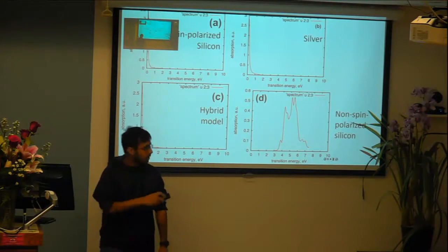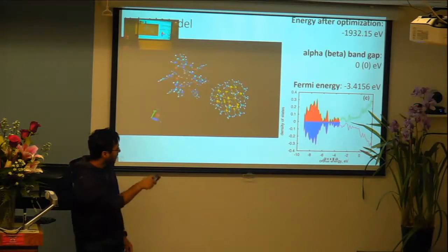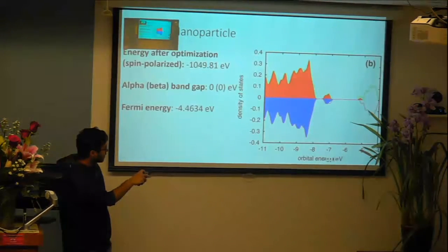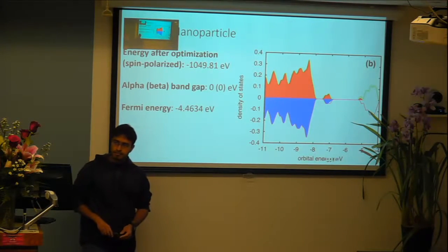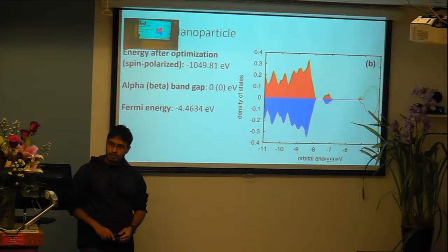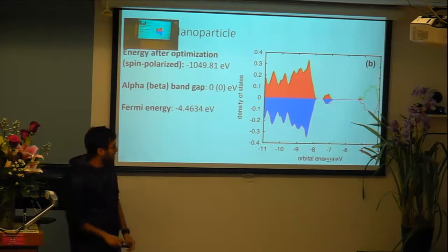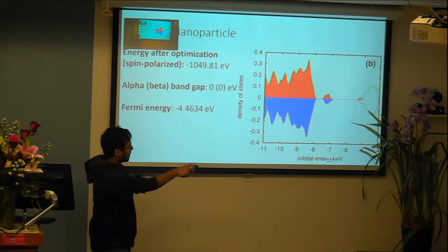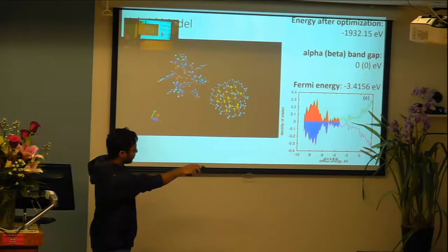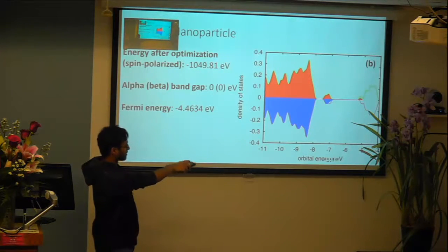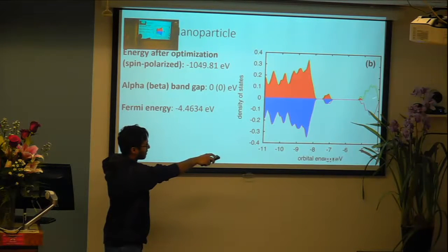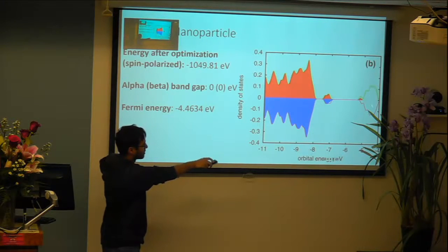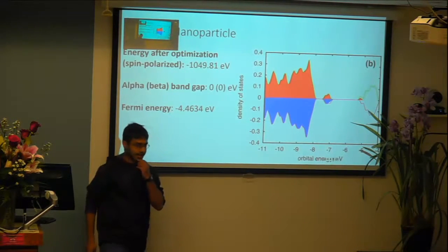Right, yeah, so here we can see from this figure that HOMO and LUMO are very close to each other, so the band gap is essentially 0, and the same thing actually occurs right here. You can see that this final state that is occupied is only partially occupied, and right next to it is an unoccupied state.